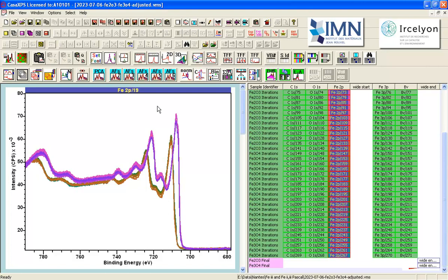Now that suggests that we have different material properties here. That although the spectra look very, very similar, one of them is capable of moving charge from ground, because both are connected to ground, through the material and provide a potential at the surface during the measurement by XPS. Whereas the other one, no electrons are coming from ground, and only the electrons that are arriving via the charge compensation are altering the potential of the sample.